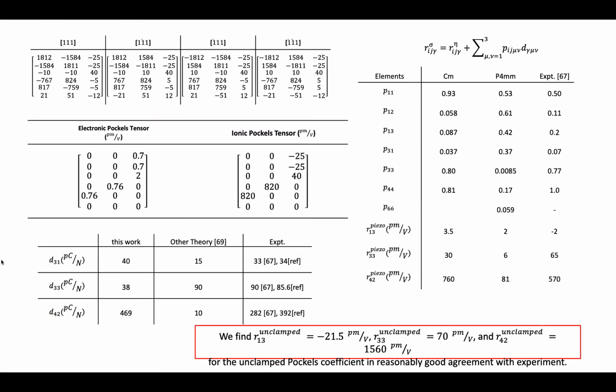And the only problem is, so this is the ionic response. So this is 820, this is just ion. So that's what you call the clamped one. And then we can calculate the unclamped one by looking at the piezo response. All of this works more or less well. So we get the right numbers. The only problem is you can't cheat nature, right? This is a highly anharmonic system. So I'm looking at the potential surface, which has nothing to do with the real thing. You need to look at the free energy surface.